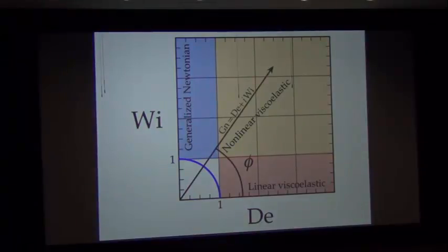I want to come back to the Pipkin map here with three colors. Blue, that's behavior along the y-axis here, that's the steady shear viscosity curve. So when there's no elasticity, when the frequency is low, that's the same as measuring a steady shear viscosity curve. If I make the Weissenberg number small, then I'm exploring the behavior along the x-axis, that's the small amplitude oscillatory shear experiment that we talked about earlier. And then I think the most exciting region here is this region, where we have high elasticity and high nonlinearity. If we think of this in terms of plastics processing, pressure-driven flow through a long tube, that might be the spinneret, for instance, pressure-driven flow through a hole in the spinneret to make fiber. That would be what goes on along this axis here.